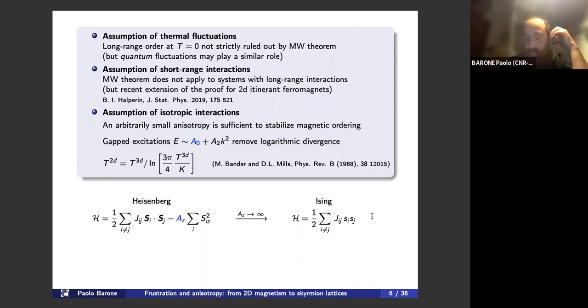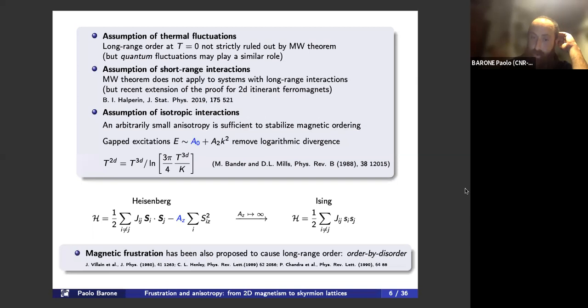Let me also mention that during the 80s, another possible mechanism has been proposed to cause long-range order in low dimension. It was proposed originally by Jacques Villain, and it's called the order by disorder mechanism, and is strongly related, of course, to the presence of frustration, which in some cases is enough to reduce the symmetry from the continuous one to a semi-continuous or discrete symmetry.